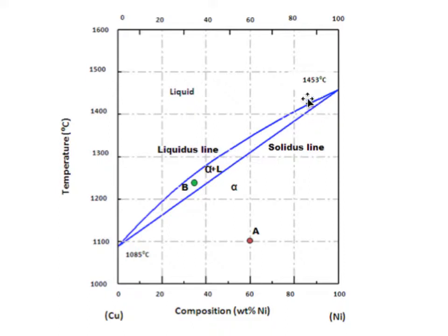We can also recognize this line as a solubility line, as we discussed before. It shows in principle, down here, the solubility of nickel in the liquid copper melt. We can also see the solidus line here. And it can be regarded as a line where the material starts to melt. I mean, for all these compositions we can read here when the melt starts, when we increase the temperature. When we come up to the solidus, we start getting some melting.